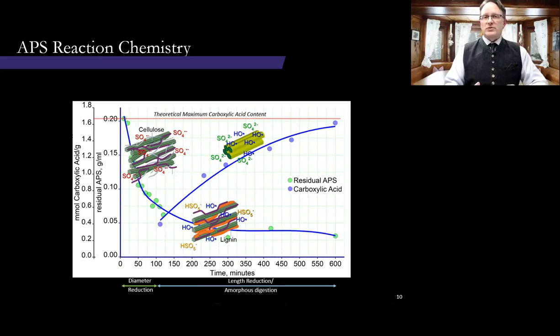One thing I think that's really interesting and unique about ammonium persulfate is the hydrogen sulfate ion and peroxyl radical can also form what's called Caro's acid. And Caro's acid is a very strong delignifying agent, and maybe what's responsible for why ammonium persulfate can tolerate lignin-containing biomasses, and that's represented here.